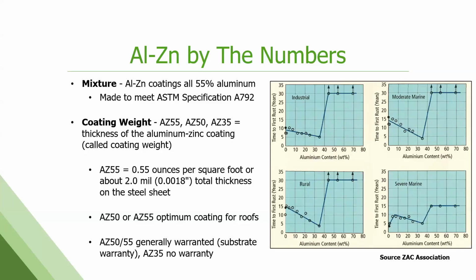Coating weight. So we can put different amounts of this metallic coating on the steel. AZ55, AZ50, and AZ35 are the three most common here in the United States. This is a weight. So AZ55 is 0.55 ounces per square foot. It's about 0.0018 inches total, but that's split between both sides of the steel. AZ50 at this point is probably the most common coating weight we see called out in the specs and the most common that's getting used for painted product. Still see AZ55 being used for bare applications because you just want a little bit more protection on there.